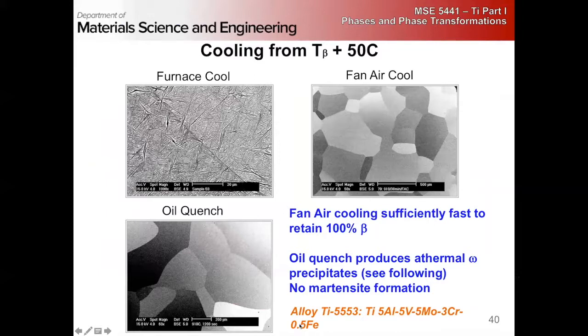And so here we have titanium 5553, right? So aluminum, vanadium, molybdenum, chromium with a tiny bit of iron. And we can see the different structures that we get, this is cooling from above the beta transus plus 50 degrees C. Slow furnace cool, we get a very large prior beta grains with a basket weave type structure. Air cooling, we essentially retain 100% beta.